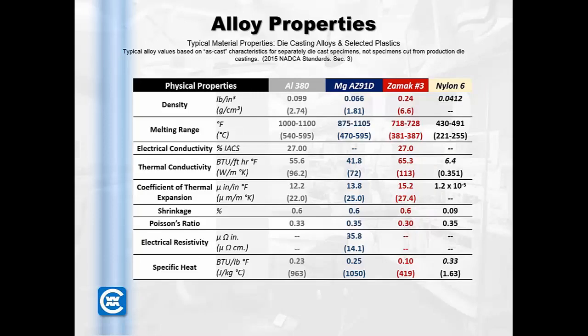The second screen for alloy properties, again, a couple things to point out. When you look at the relative densities of each of the alloys, magnesium is by far the lightest. It's the lightest structural metal alloy out there. Pretty much on par with plastic, actually. They're fairly comparable weights, so a lot of times people are able to convert a plastic part over to magnesium, not affect your overall product weight, but get far better material properties. So magnesium is the lightest weight.